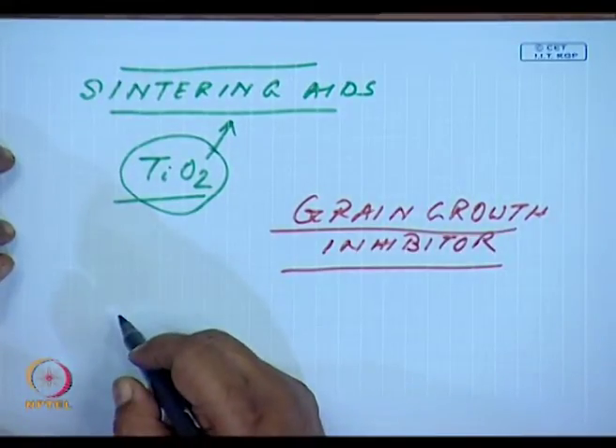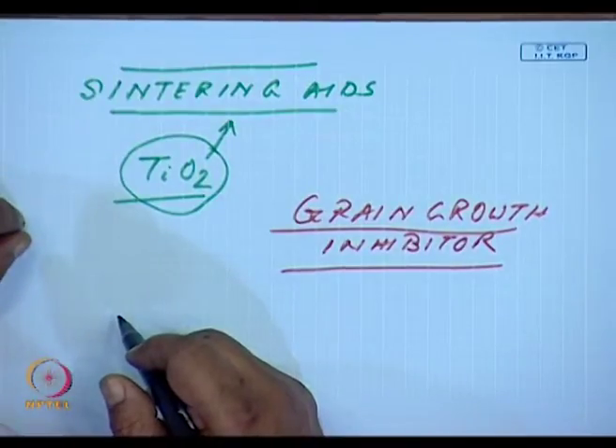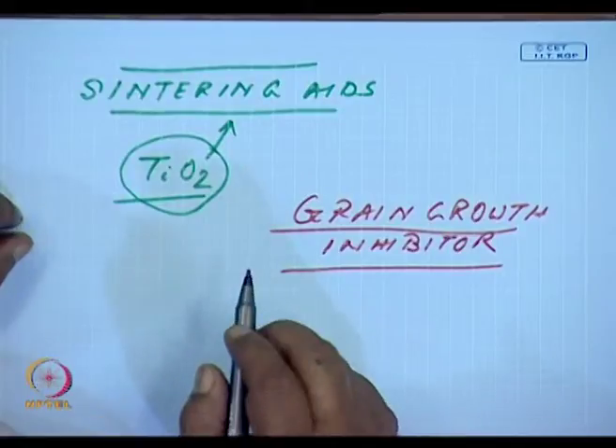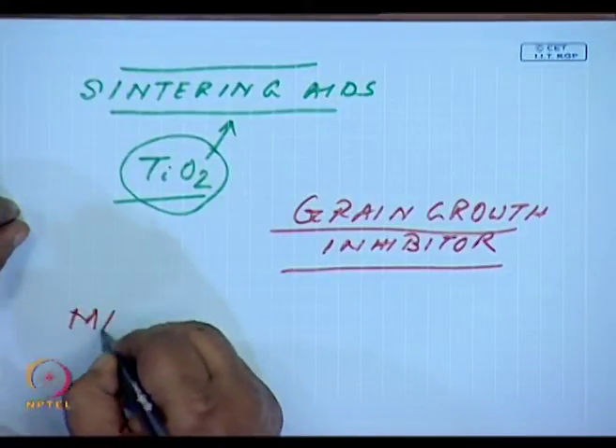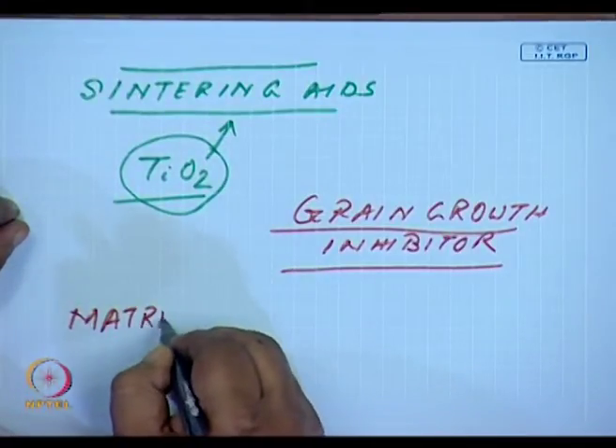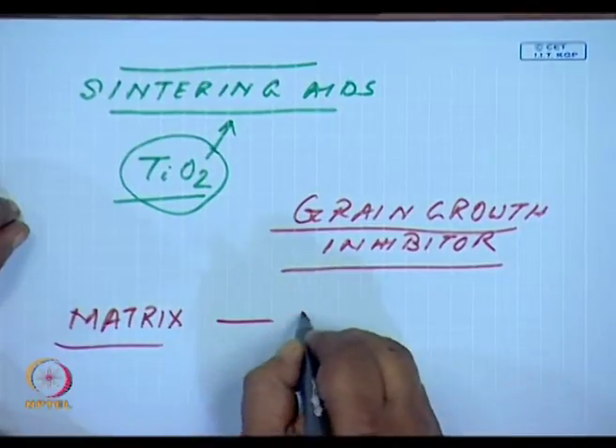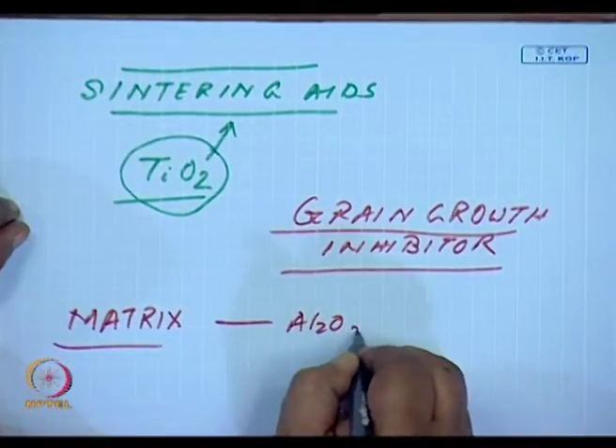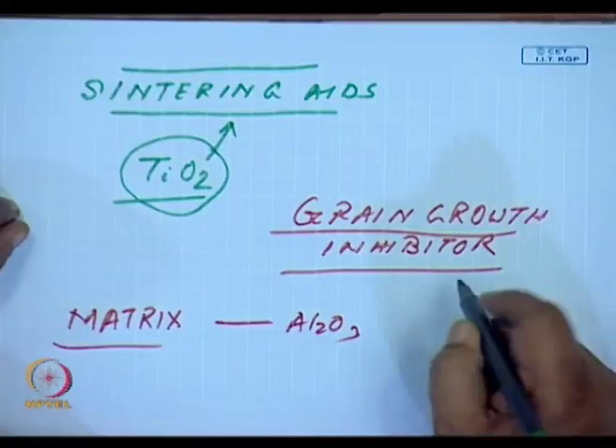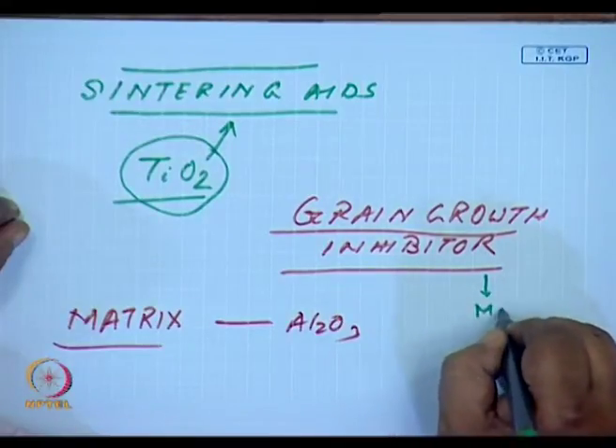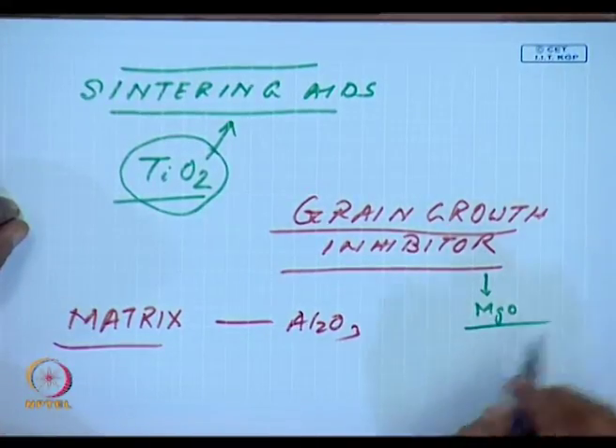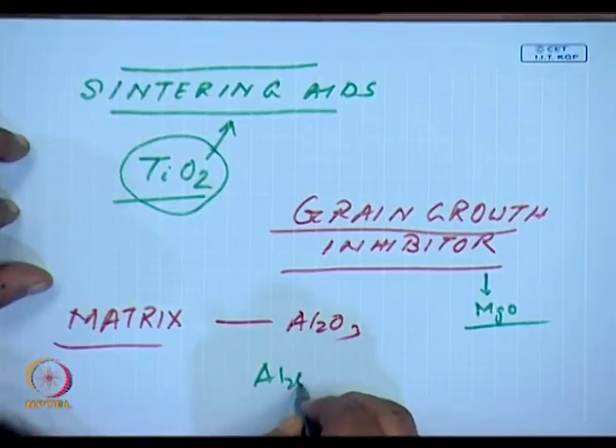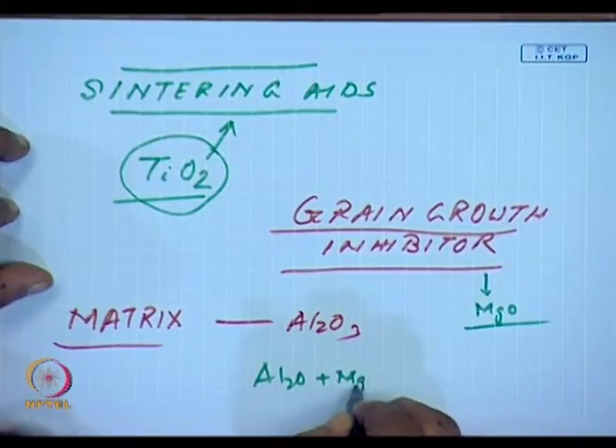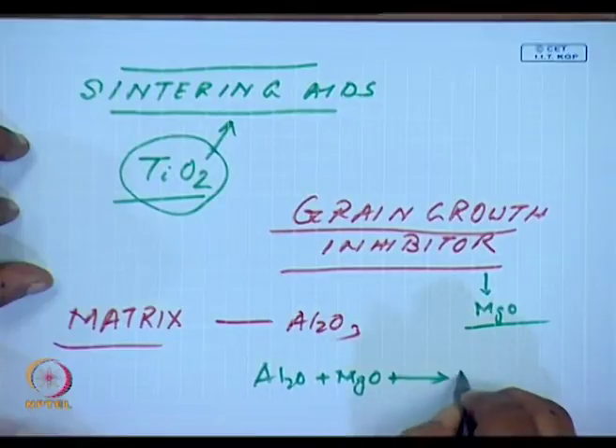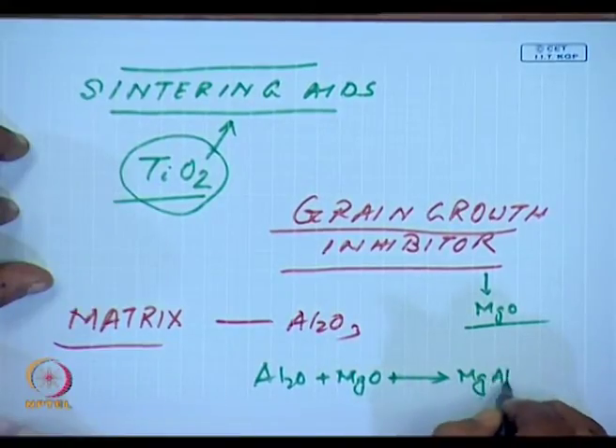So that none of these grains could grow. Because that matrix from which the sodium vapor lamps are made is based on alumina, the grain growth inhibitor used is MgO, as alumina reacts with MgO to give you MgAl2O4.